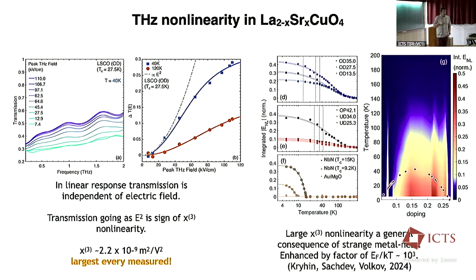And so what it looks like, and this goes along with the idea that the nonlinearity is basically related to linear T resistivity. Because from your work, we think that we lose any contribution of linear T at that point. And then the nonlinearity seems to be going away. Yeah, so that seems to tie together. That's a point we make in the paper.